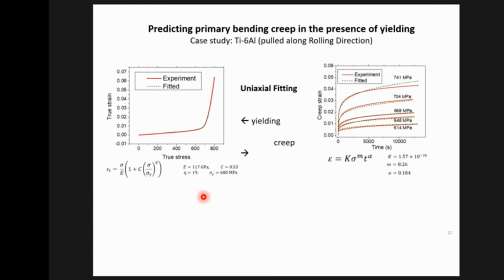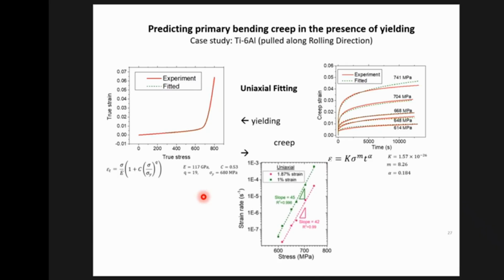Now, we set about trying to model this exercise. I won't labor this too much, but basically, you're working here at stresses where the material may have yielded. These are extremely high stresses at which creep is taking place, which is very different from high temperature creep, where you're at a small fraction of the yield stress. So we fit the uniaxial behavior, the stress strain curve, the creep curve, and then we use that to predict what will happen in bending. This is the reverse of what we want to do, but this is just to see if what you measure is consistent with what you predict.